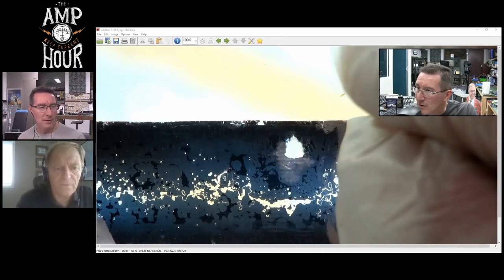Yes. It's pretty neat to throw these on a sample scope and apply a couple of different signals to them. You'd actually see some noise occurring when we have self-healing events. What sort of noise are you talking about? Well, you'd apply maybe full voltage at a moderately high temperature, and you might see some failures punching through, and you'd see some variation in the applied voltage of the part as this thing coronas. So when you get those little micro healing points, you actually vaporize that electrode material, and as it cools, it precipitates around that failure site.